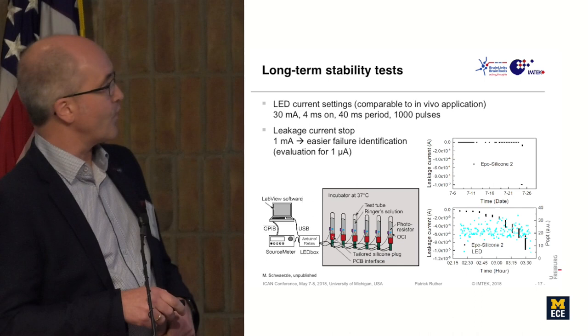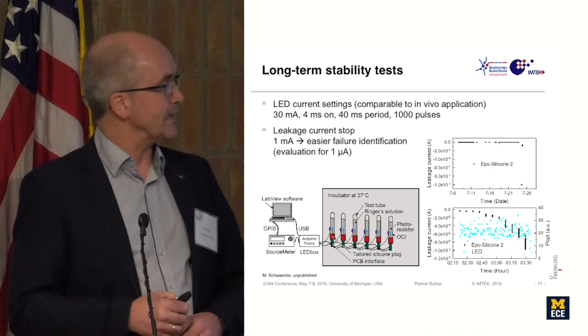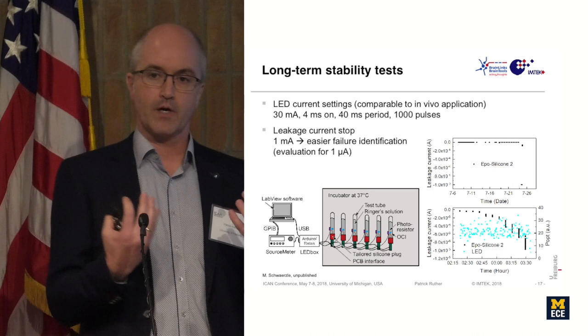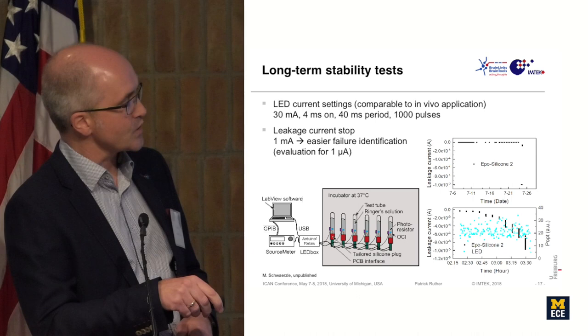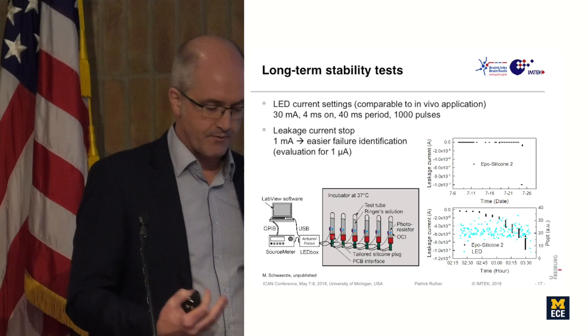And the probe fails when the leakage current exceeds 1 microamp, but we of course tested it up to 1 milliamp of leakage current to see corrosion in the devices. And what we see here when we look at the leakage current as a function of time, we see a sudden and abrupt failure of the probe itself.